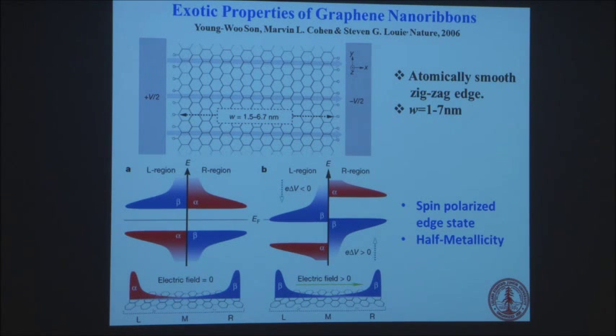And if you calculate the electronic property of such a ribbon, the edge here actually can give you localized states. So states can be localized at these edges, and they can also be spin polarized, which is very, very exotic. In other words, the spin of the states on one side of the edge is gonna be spin up, and on the other side, the spins will be going down, and it's antiferromagnetically coupled. And you can use electric fields to manipulate these edges so that it's all spin down. So it becomes a spin filter, right? So only this spin can pass.